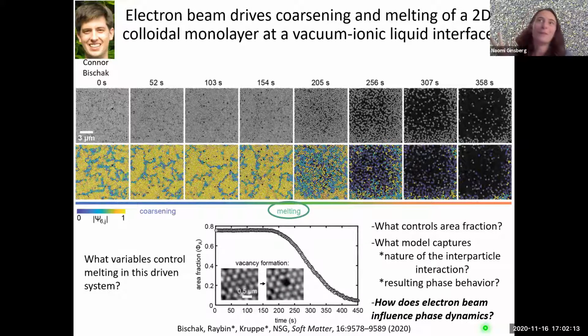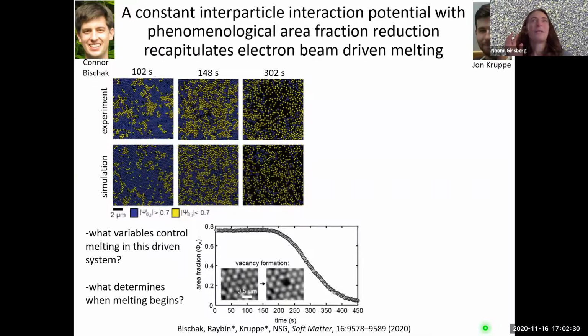And I'll focus on the one that's most consistent, folding in each of the necessary considerations in sequence. So to start, assume for now that the area fraction can be controlled, and I promise I'll return to this and verify that assumption too. Okay, so here are binarized maps at 3 different times of the same data set. So here blue is ordered and yellow is disordered.